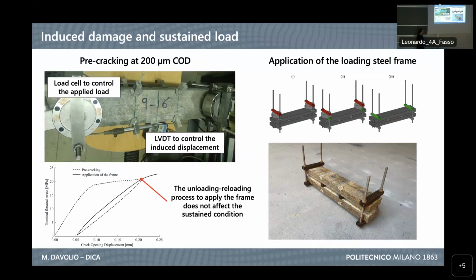The idea of this was to reproduce the pre-cracking condition, but as we know, after pre-cracking with the machine, we had to unload the specimen before reapplying the load. So we verified that reloading it at a specific load, which was the same we achieved during pre-cracking, obtained the same crack width we wanted to have. And for this, we calibrated the system and we observed it was as we expected. So the condition we see here is the same as pre-cracking.